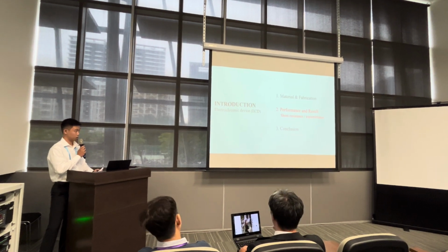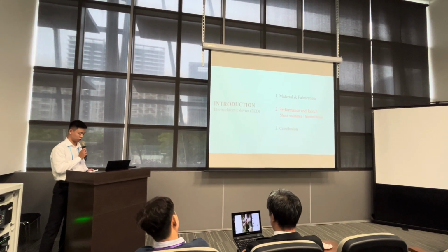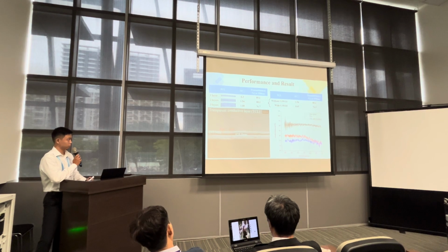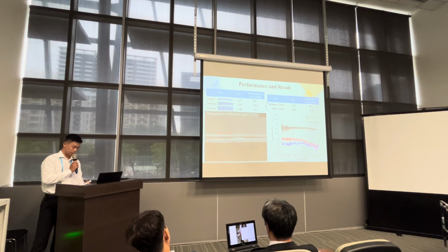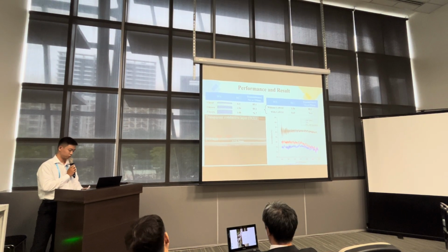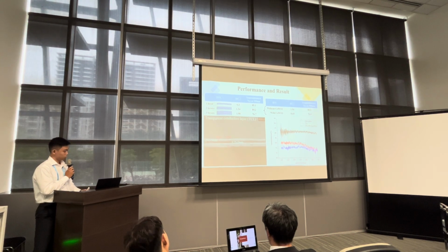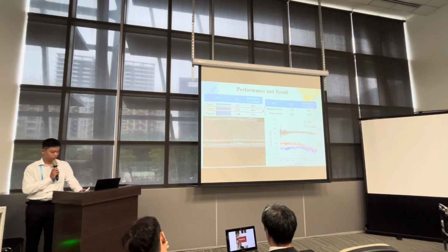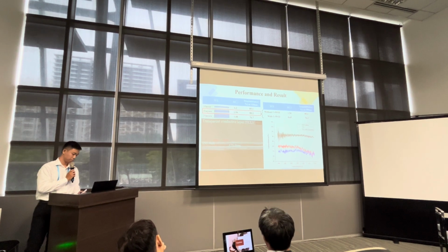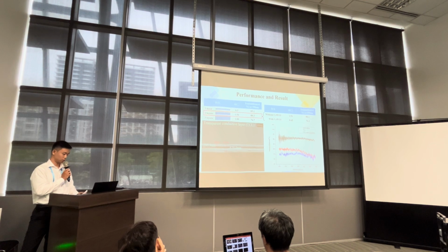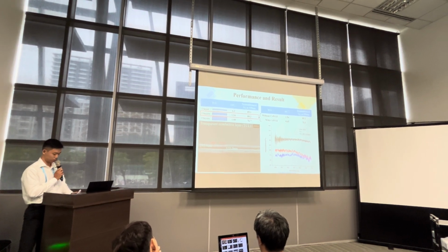Next, I'll report the results of our transparent conductive oxide. On the left side, the table shows that we compare the features of the 1 layer, double layer, and triple layer. The thickness of each layer is approximately 300 nanometers. We find out the double layer one has the most ideal combination of sheet resistance and visible light transmittance.